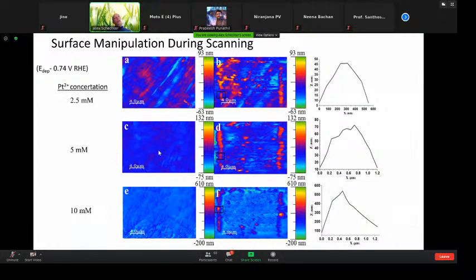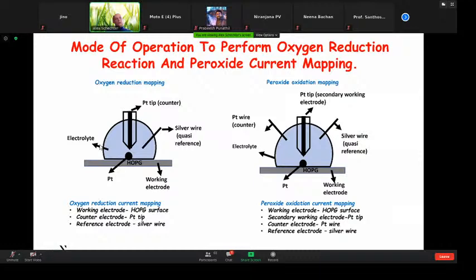Then we set ourselves to measure not just the oxygen reduction on a single particle, but also the reaction of the byproduct. To do that, we had to modify the setup a little bit, and we went from three electrodes, meaning the electrode down here, the HOPG, and a silver reference electrode, to adding a secondary electrode. And the reason for doing it is because we could scan the electrode and see the oxygen reduction, and then repeat the same measurement and scan the